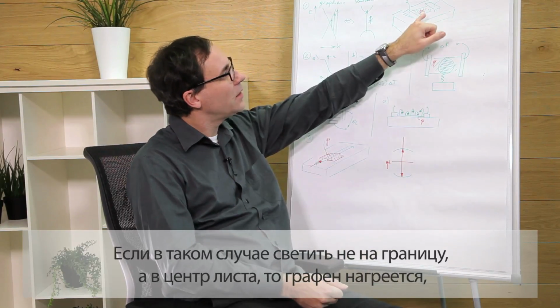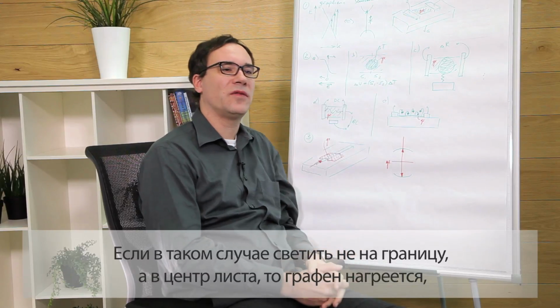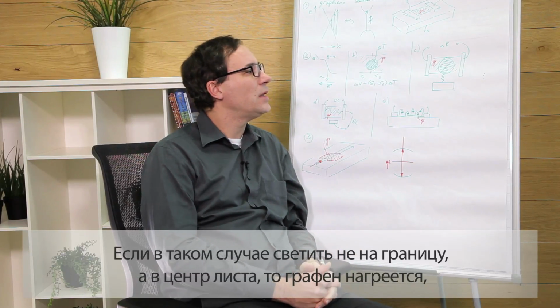A third effect can be observed if we suspend the graphene sheet in air, so thermally isolated from our environment, for example, and we shine the light not at the interface but right in the middle of this sheet. What we see then is that we heat up the graphene sheet, so we get an elevated temperature there. Because of this heating, the sheet changes its resistance. You can now sense this resistance just by applying a small voltage between these two leads and measuring the current flow.